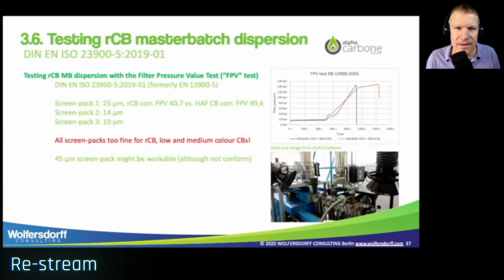Now let's go to testing recovered carbon black master batch dispersion. And here I'm thankful for the data from Alpha Carbon and the fact that they allowed me to show this data. We said that the color performance is very dependent on the dispersion. And how do we test dispersion? There is an international standard for the filter pressure value. Here we are extruding with a screen pack, and we're measuring not the particles that are on the screen pack in ppm, but we're measuring the counter pressure, which increases, as you can see on the right-hand chart, with the amount of extruded master batch.